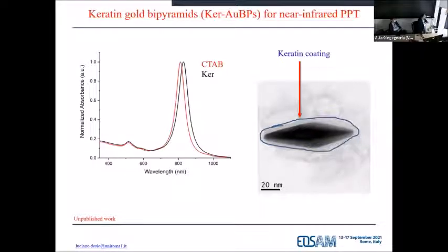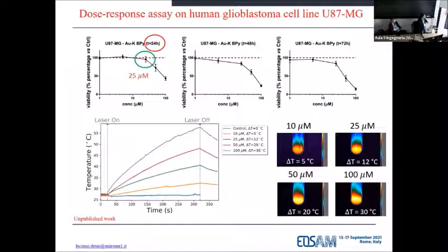And once we had those particles keratin coated, immediately we went to the lab to see if the biocompatibility is very high now. And we weren't really happy, because you can see that if you increase the concentration above 25 micromolar, there is a toxicity of those particles, because most likely there is a lot of residual CTAB, and our layer is not enough to coat those particles.